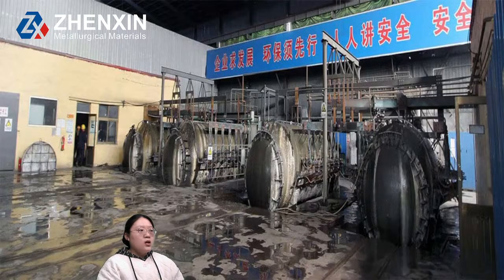That's when we use rare earth nodulizer. But when is non-rare earth better? When base iron is clean, thin wall casting, fast production.